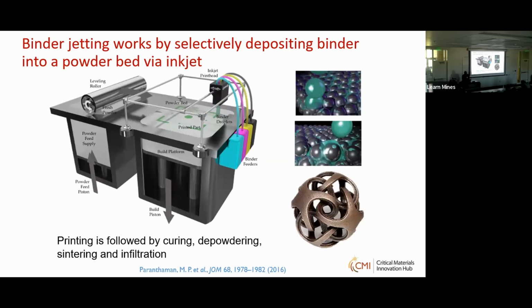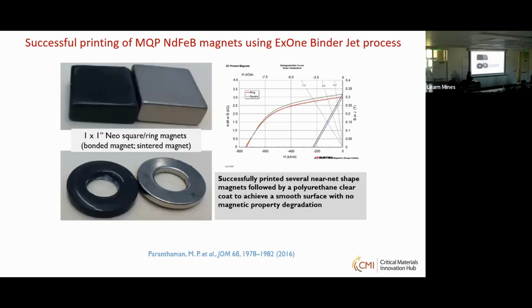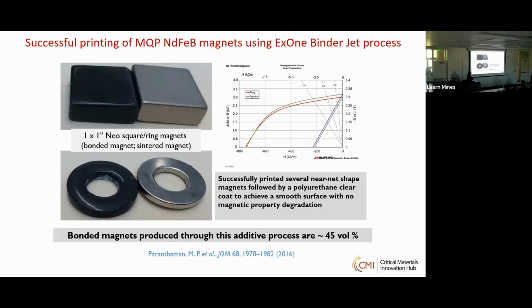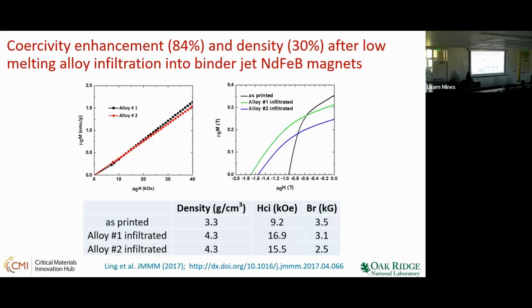We did some binder jetting process in the past. In 2016, we made sintered magnets and ring magnets. We compared the properties. It's about 50% dense, 45 volume percent, so it's a weaker magnet, but you can still use binder jet as a method for making magnets. Then we also did some infiltration using different alloy compositions, praseodymium and copper alloys. So we could improve the density of the magnet and the remanence and coercivity. I think the remanence will decrease a little bit. So there are things you could do with this.